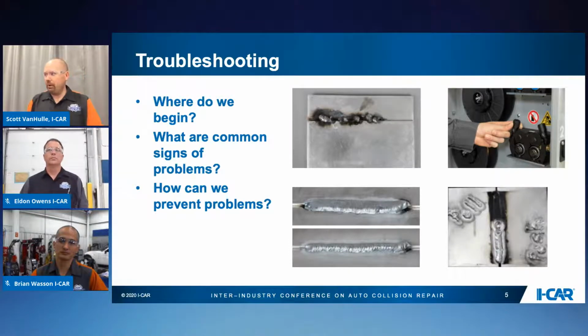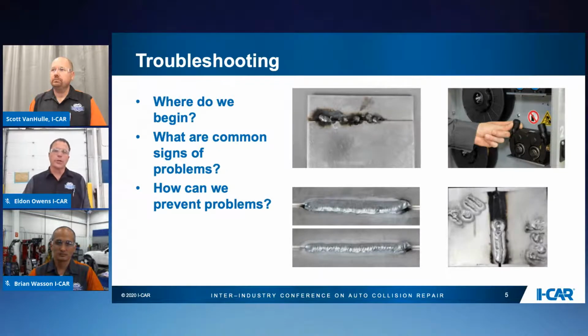So, in the upper right picture, we have the inside of the machine. What are some troubleshooting things that we're looking at when we're looking at the rollers and the adjustments? Again, just making sure that the correct roller is in the machine, and also the size of the roller groove for the wire to feed through. If we're trying to run 1.0 wire through a 1.2 roller, we're going to have slippage, and that's going to create some wire feed issues. So really going back to basics: if we're having a variable arc that's changing back and forth constantly, that really comes down to a wire feed issue, and we need to check those things out.